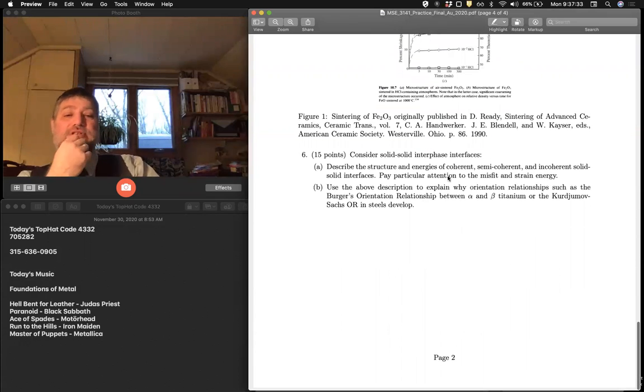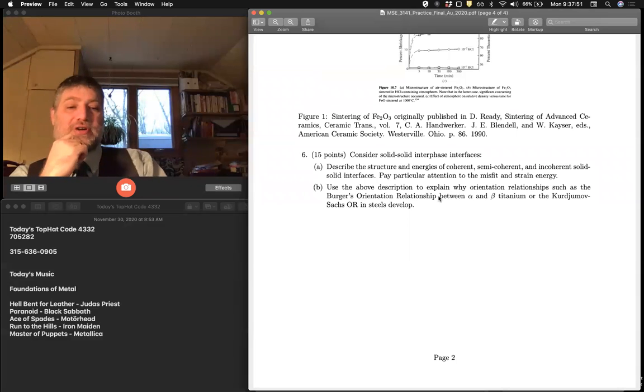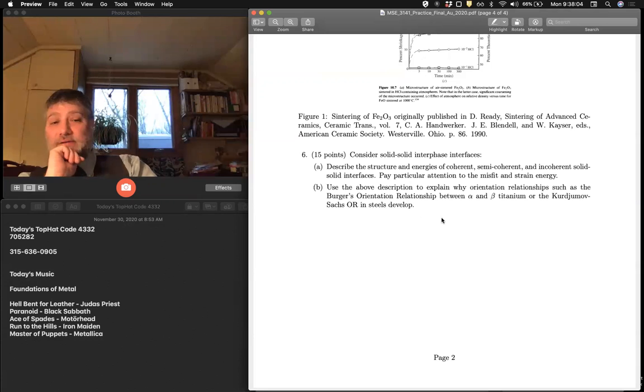And then the last question is about interfaces. So describe the structure and energies of coherent, semi-coherent, and incoherent solid interfaces, right? Pay particular attention to the misfit and strain energy, and use the above description to explain why orientation relationships, such as the Burgers orientation relationship between alpha and beta titanium or the Kurdjumov-Sachs orientation relationship in steels develop, right?